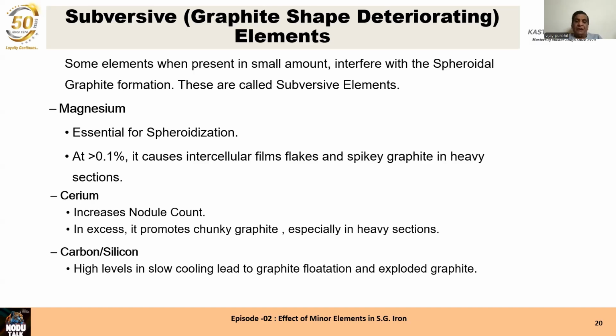Cerium is required to be present for two reasons. One reason is it is a neutralizer. It neutralizes the bad effect of all the subversive elements. So cerium is required because we can't check each and every piece of scrap that we are using. We do not know what subversive elements are present. So not knowing what subversive elements are present, we always use cerium as a mixed metal or rare earth in the magnesium treatment alloy. Cerium is required to increase the nodule count. It also causes chunky graphite formation if it's at a high level.